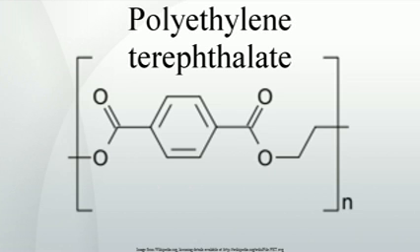An article published in the Journal of Environmental Monitoring in April 2012 concludes that antimony concentration in deionized water stored in PET bottles stays within the EU's acceptable limit even if stored briefly at temperatures up to 60 °C (140 °F), while bottled contents, water or soft drinks, may occasionally exceed the EU limit after less than a year of storage at room temperature.